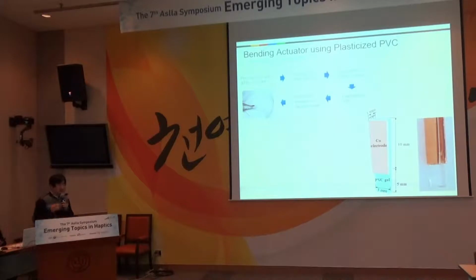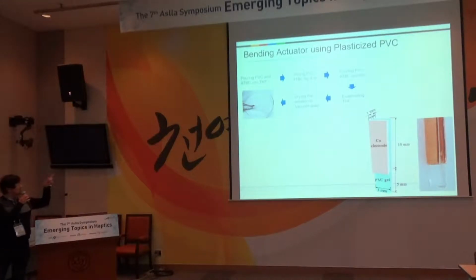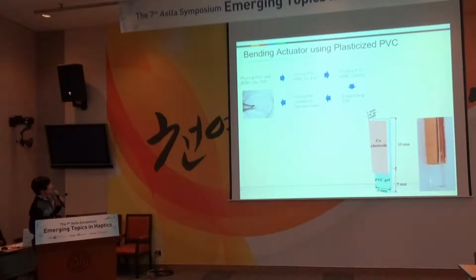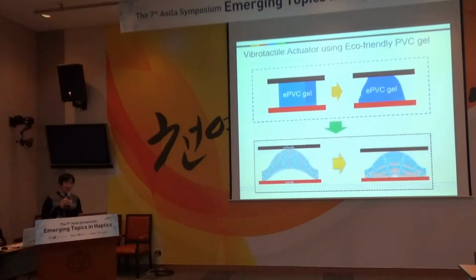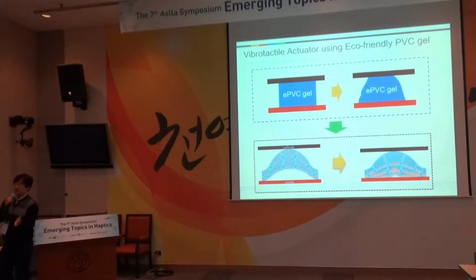We can make the plasticized PVC like that. First, we pour the PVC powder and ATBC solution into the THF and stir it. Then we pour the PVC ATBC solution into a beaker and dry it. So finally, we can get this kind of plasticized PVC gel. So we're ready to make the soft vibrotactile actuator.